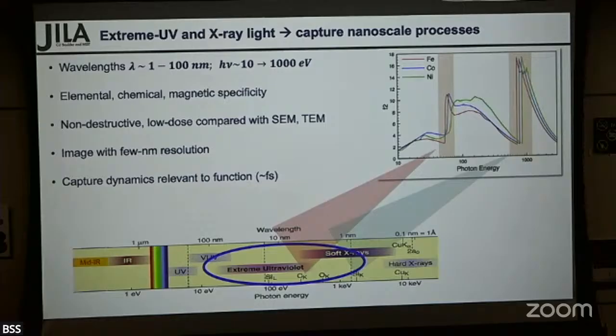So it's a very powerful readout, and you also add time resolution, and you can suddenly see, for example, spin moving around if one is exciting material with light, or generating a spin current or such. On top of that, because the wavelengths in the extreme UV and soft X-ray region span from perhaps 20 eV to a keV, those photoelectron energies, when you shine that on a material, are much, much softer than in a TEM or an SEM. So you can do a non-destructive probe or non-destructive imaging of even a soft material.